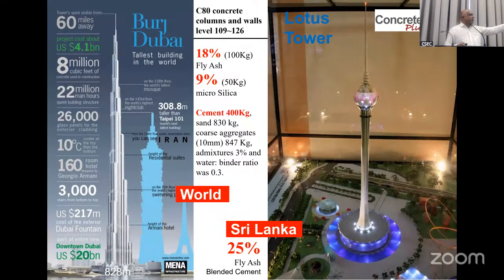That's why in the Burj Khalifa, this is grade 80 concrete. You can see how much cement they have used, only 400 kilograms. This is OPC, plus fly ash 100 and silica fume 50, altogether 550. And they used admixture 3%, water-cement ratio 0.3. And of course, aggregate size they have reduced to 10 millimeter because of pumping. As I mentioned, even though there are 100 standards, if you stick to the basics, you can make things last for years.